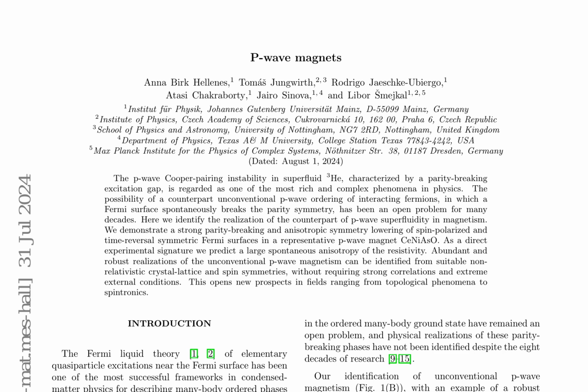By focusing on suitable non-relativistic crystal lattice and spin symmetries, the authors demonstrate the anisotropic symmetry lowering of spin-polarized energy isosurfaces in a representative p-wave magnet, CeNiAsO. The authors utilize density functional theory, DFT, calculations to confirm the symmetry principles underlying this unconventional magnetism. They observe that the parity breaking of spin-polarized energy isosurfaces is accompanied by an additional anisotropic distortion.